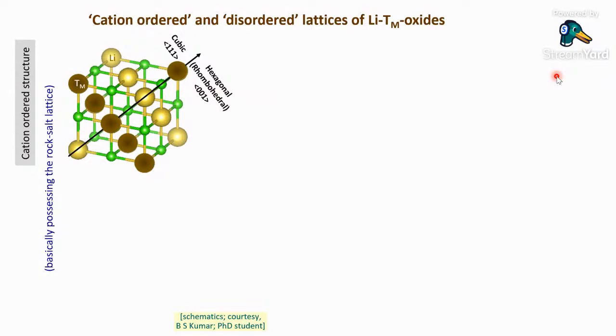Now, before trying to understand what happens to the structure of the cathode material, again, from the point of view of those who may not be very familiar with the structure of these materials, a very simplistic view can be presented here. So, what we usually call a layered transition metal oxide, the word layered actually refers to a cation ordered rock salt type of structure. So one can see that this is a rock salt structure with a cation being of two types: transition metal ion like cobalt in case of lithium cobalt oxide, or nickel cobalt manganese combination in case of lithium NMC, and lithium ion. So these two types of ions make a cation subunit cell, and the anion subunit cell is made up of oxygen.